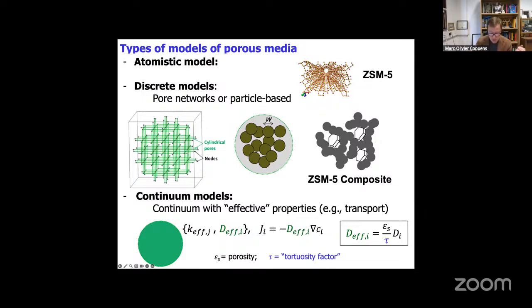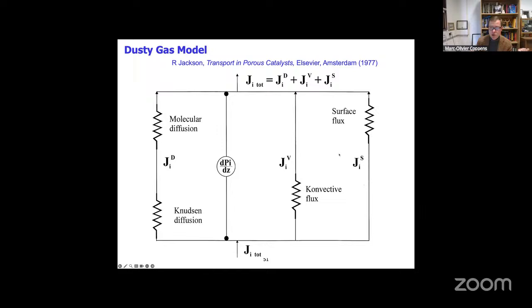And something I also didn't really talk about, I just skimmed over it, is that you have surface fluxes, you have surface diffusion. So if you have higher pressures or lower temperatures, you may have a significant flux alongside the surface. This needs to be included. There's beautiful work on membranes by Andreas Seidel-Morgenstern and colleagues, who also demonstrate the importance of the surface transport, right?